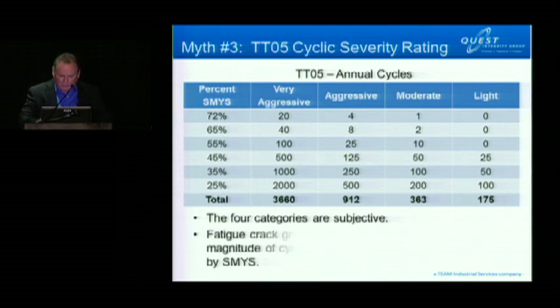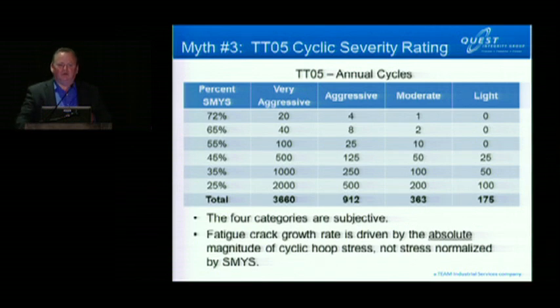But the more serious problem is that when you do a fatigue crack growth calculation, the rate at which that crack grows is a function of the absolute cyclic stress, not the stress relative to SMYS. Whereas this is all normalized by the yield strength, but the real world doesn't work that way. And so as I'll show you in a moment, the way it turns out is that you tend to be conservative for low strength materials and unconservative for high strength pipeline steels.